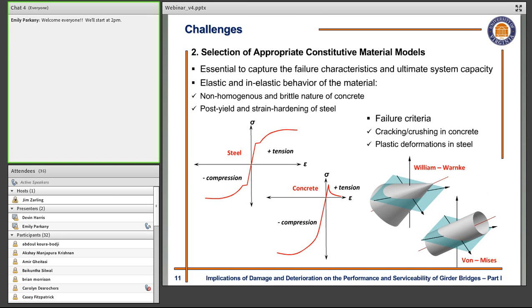And then as we take these models into the full nonlinear range, which is kind of at the core of this project, it's essential to capture the failure characteristics and ultimate capacity of the system. So we need to pay attention specifically to the elastic and inelastic behavior of the materials, non-homogeneous and brittle nature of concrete, post-yielding and strain hardening of steel. And then we also need to consider failure criteria. How do we stop the models? What constitutes failure? And for concrete, this is typically cracking, crushing. For our steel sections, this is typically plastic deformations.